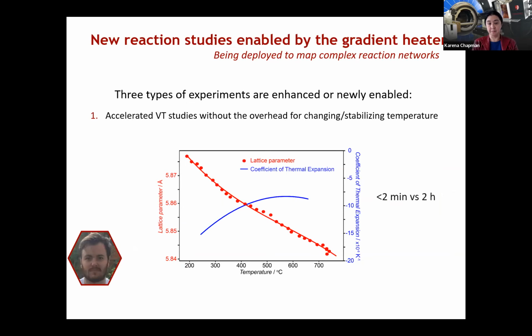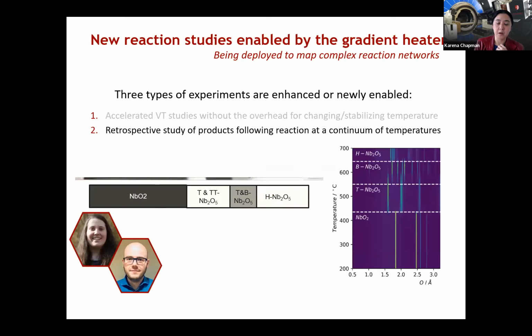This allows us now to more efficiently do variable temperature reactions. We can look at a whole bunch of temperatures in parallel without worrying about the overhead for heating and stabilizing that temperature. We can do things ex situ ahead of time or just screen a lot of different reactions - heat in this gradient, recover the sample, and then map across the sample to see what the products are and dial in exactly what that temperature is.